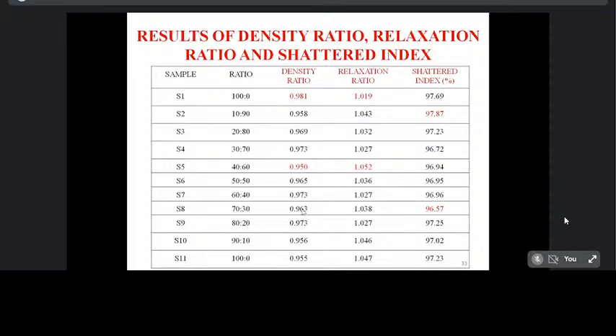Here the Shatter index, the briquette Shatter index, was determined according to ASTM for the drop shatter test developed for coal, using an equation. The Shatter index is equal to the weight of the briquette retained on the screen after dropping divided by the weight of the briquette before dropping. So we drop the briquette from 1 to 1.5 meter height. We have to drop the produced biomass briquette 3 times, and note the weight of the dropped briquette each time. So we have to weigh the produced biomass briquette before dropping, and after each of the 3 drops we also have to note the weight.